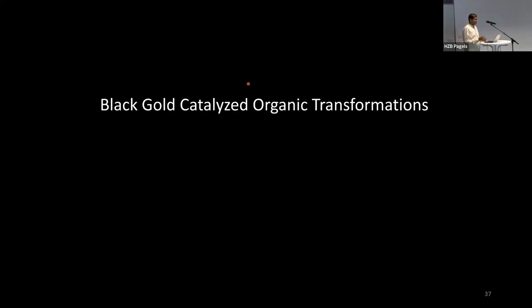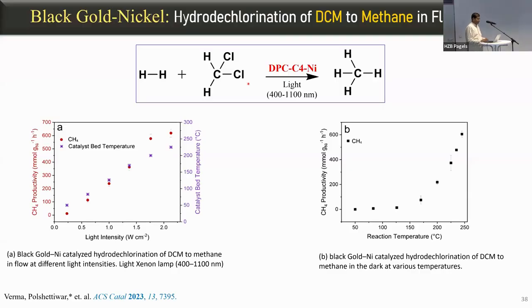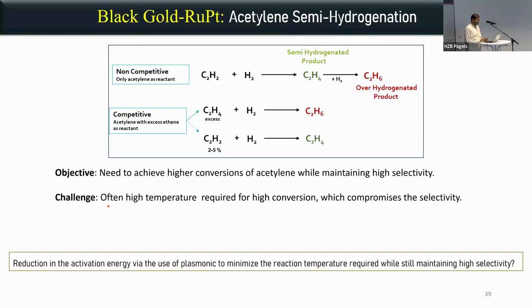So we try to explore this material for a range of other reactions other than CO2. One of which was hydrodechlorination of dichloromethane. You see the DCM, you can directly remove those two chlorines and convert this into methane. And you can again see that in dark, nothing happens up to a certain temperature, whereas in light, it happens even at room temperature.